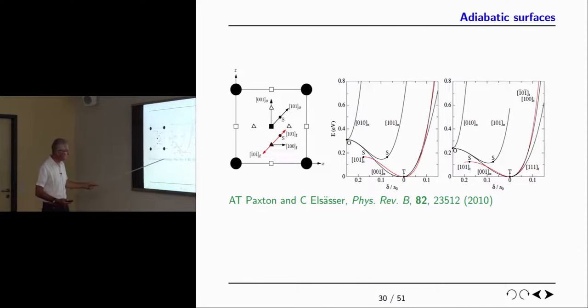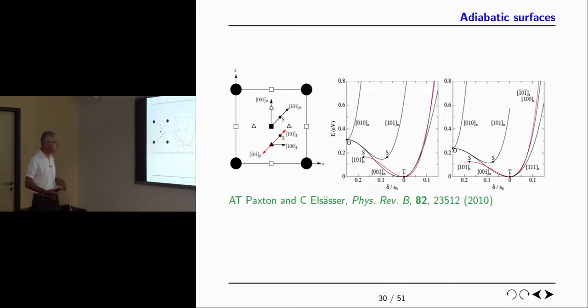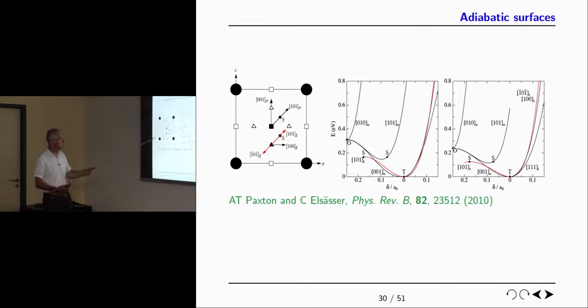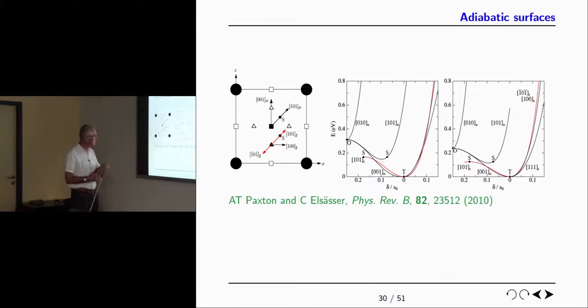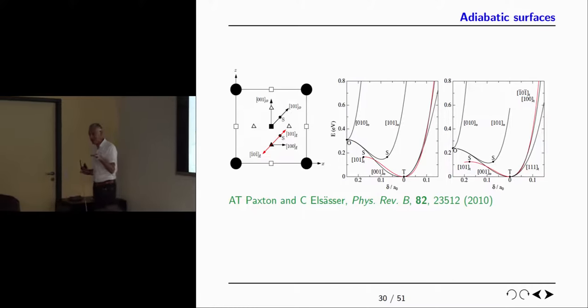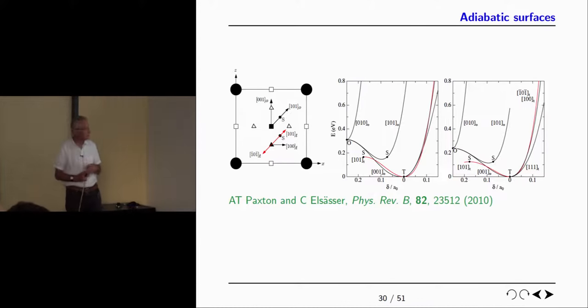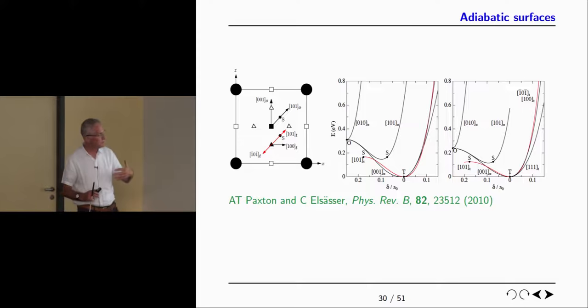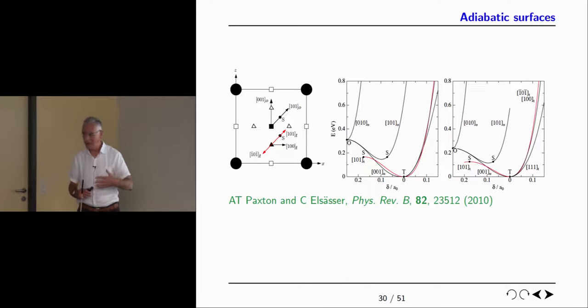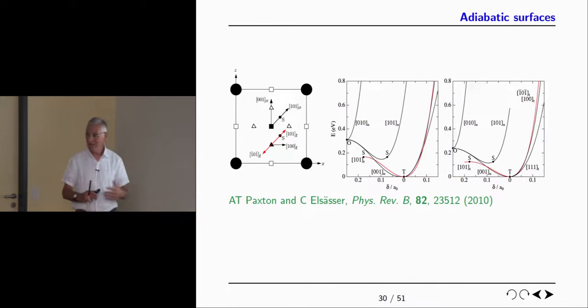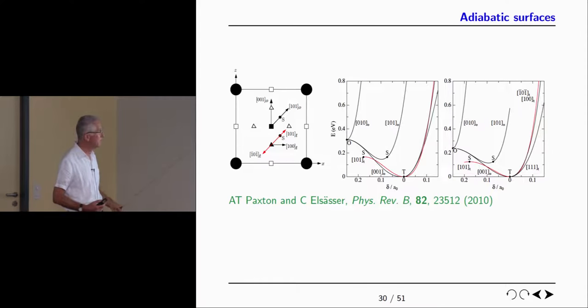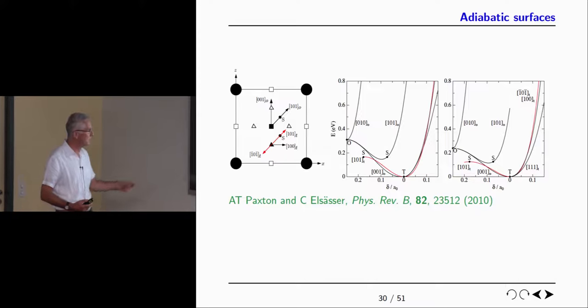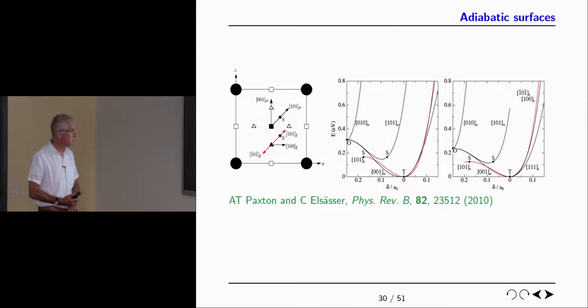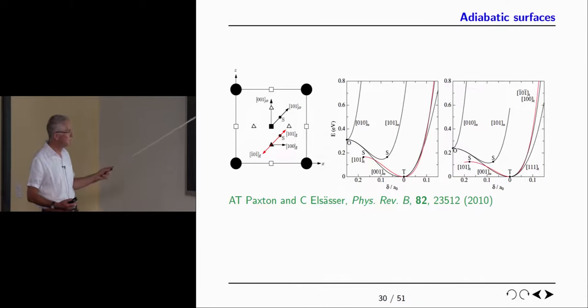Now, Christian Elsässer, who I was working with on this problem, had done previously some calculations, what he called adiabatic surfaces. So he kept a rigid lattice of FCC or BCC iron, and then he took the sublattice of hydrogen atoms in these FeH stoichiometries, and he moved them in various crystallographic directions and mapped out the total energy. And that's very important because it gives you the starting point for thinking about hydrogen movement in iron and what the energy barriers might look like.